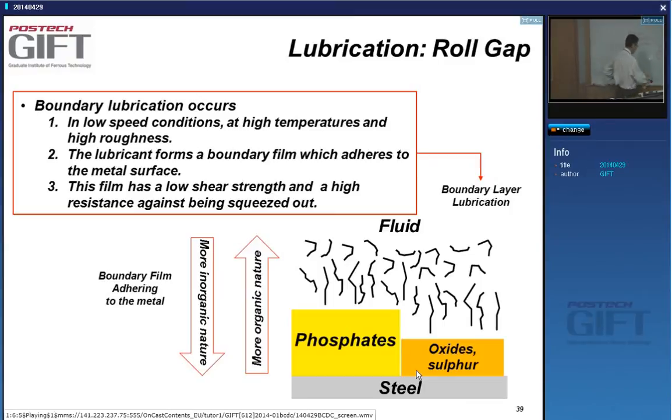So you know, the situation where the conditions become bad during rolling happens, for instance, when you have to reduce the velocity, yes? For instance, you're rolling and then you have to stop rolling because you finished the strip. The strip comes out of the mill. You have to reduce the velocity, right? Or when you're starting to roll, yes? You're not suddenly at very high rolling speeds. You build up, right? So you start at low velocities. Yes. And so in these cases, you can be in high friction conditions. Okay.